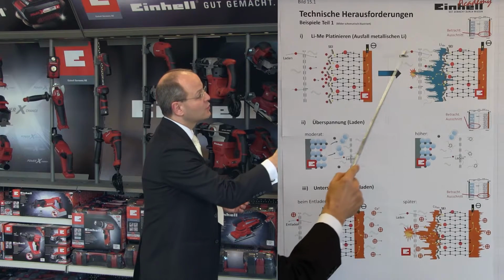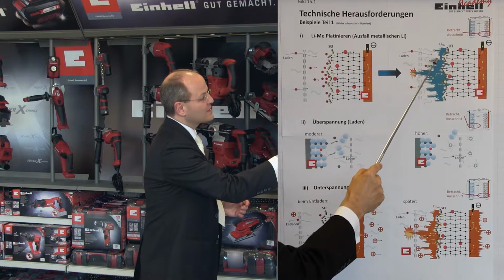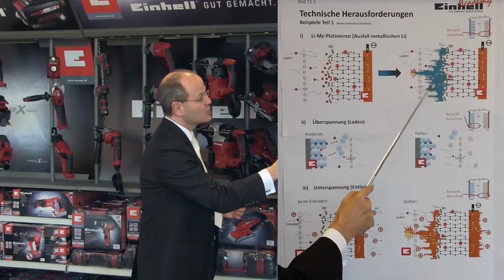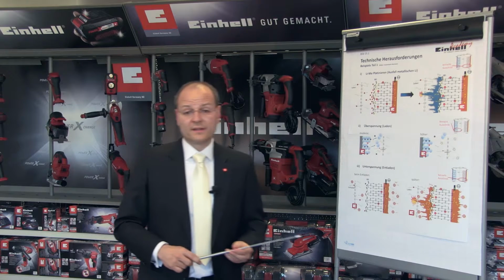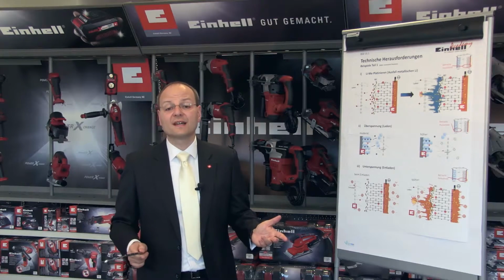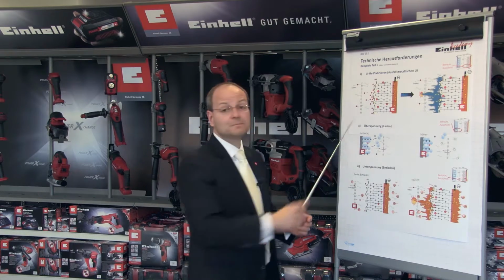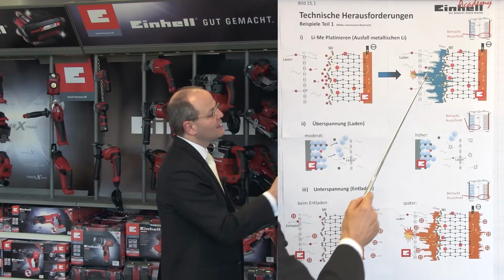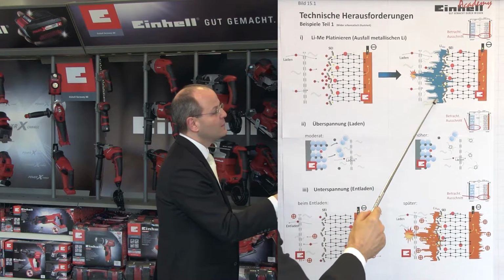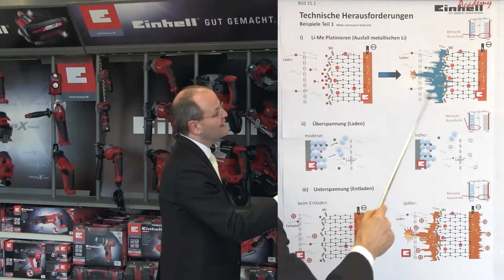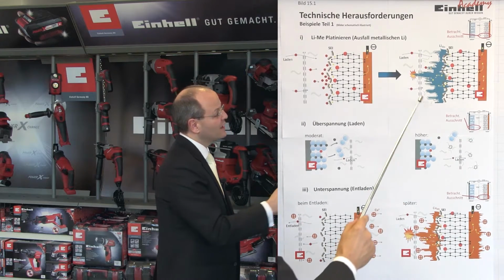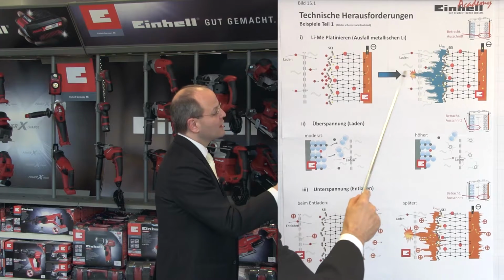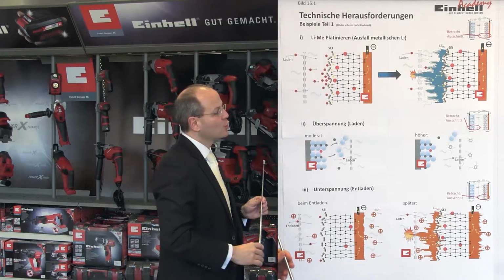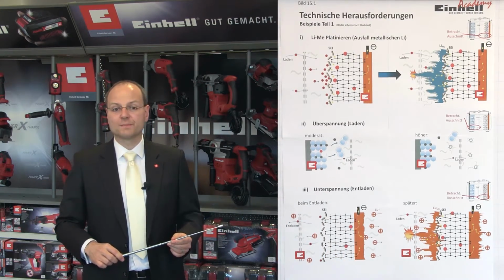Highly reactive, the metallic lithium itself reacts with the electrolyte. A passivating surface layer between the lithium and the electrolyte is produced. In this process, electrolyte is lost. The reaction products, including explosive gases, contaminate the cell chemistry. In addition, under certain conditions, the separated lithium forms a film that is not flat but instead grows in microscopically sharp needles, so-called dendrites. These can penetrate through the separator and, if they come into contact with the cathode, cause internal short circuits in the cell, known as soft shorts.